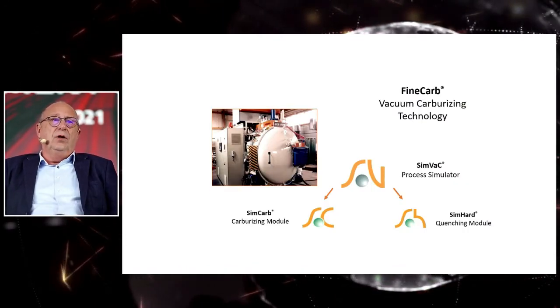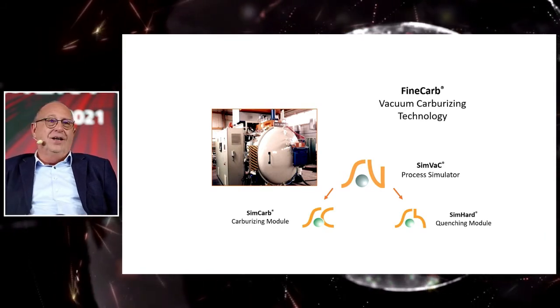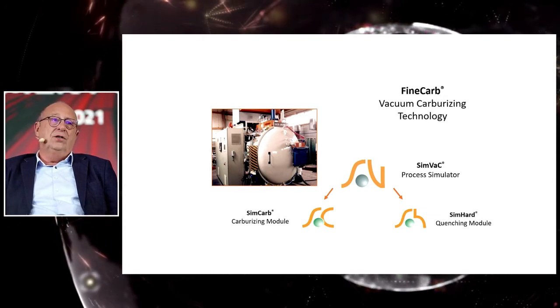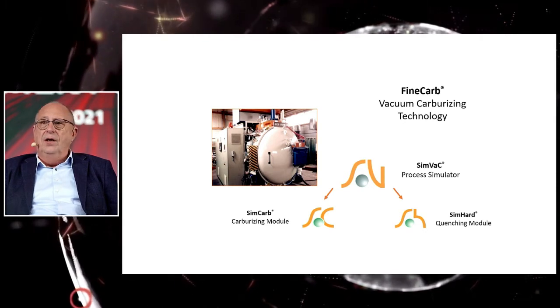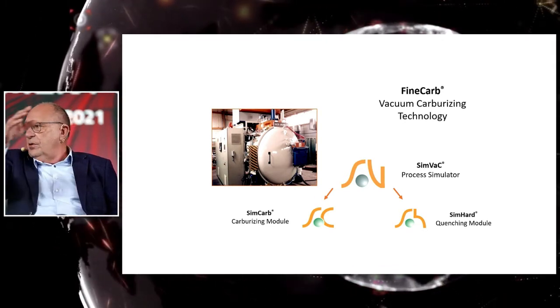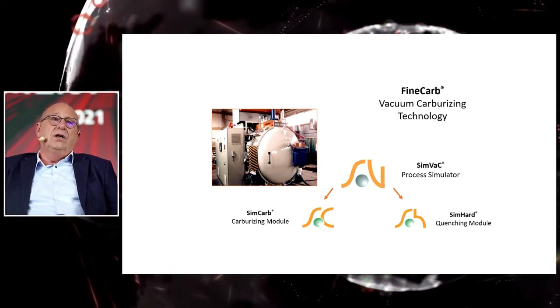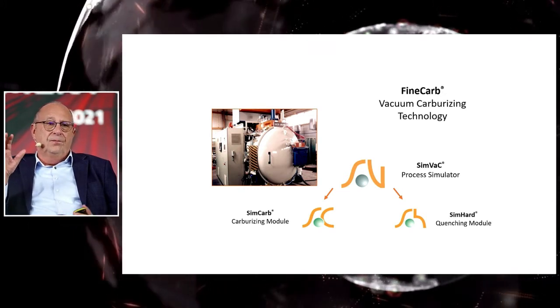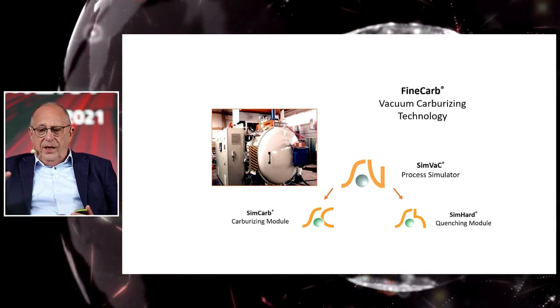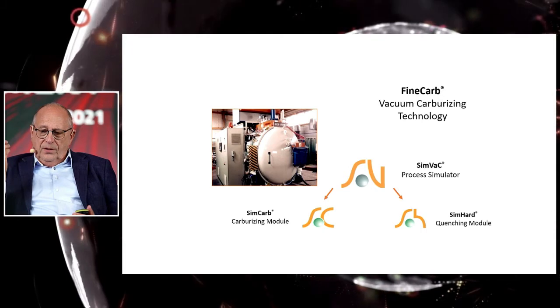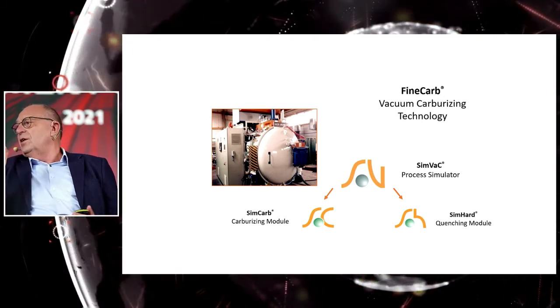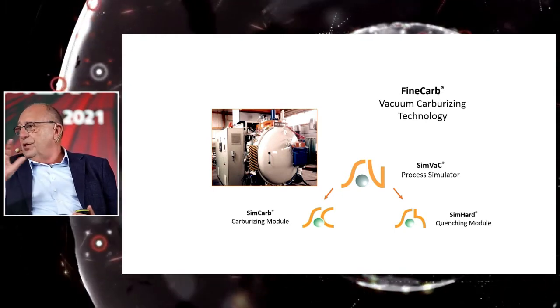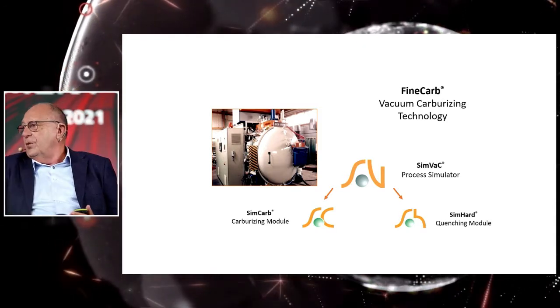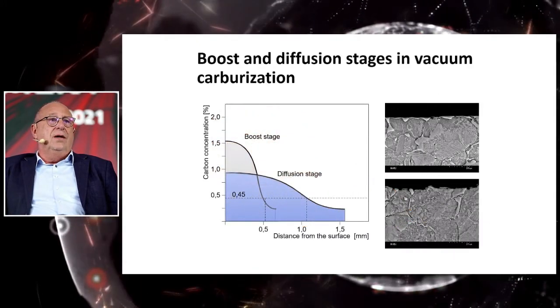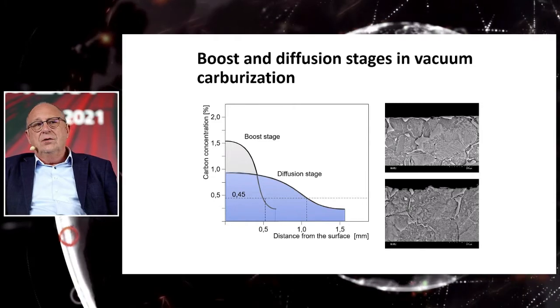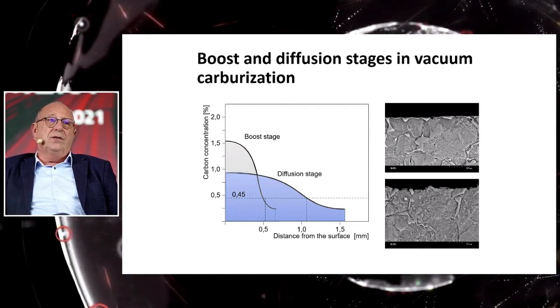For that, we developed an advanced artificial intelligence product. It is called SimVac, Process Simulator, and it consists of two modules. The first one is SimCarb, to simulate the development of carbon profile during the numerous boost and diffusion stages, and the next is SimHard, dedicated to simulating the austenite-martensite transformation in carbon-rich or poor regions to finally reach the hardness profile in the surface layer, in the case. As you can see, it is a very hard numerical challenge for that program.